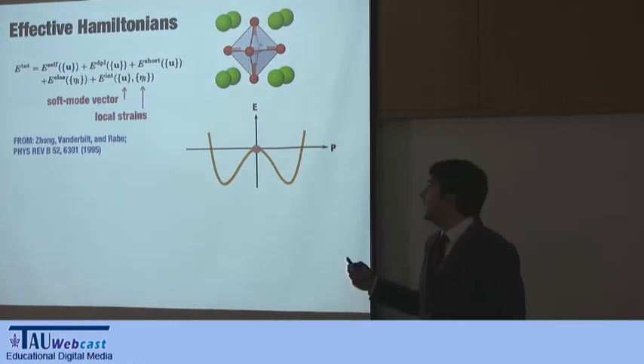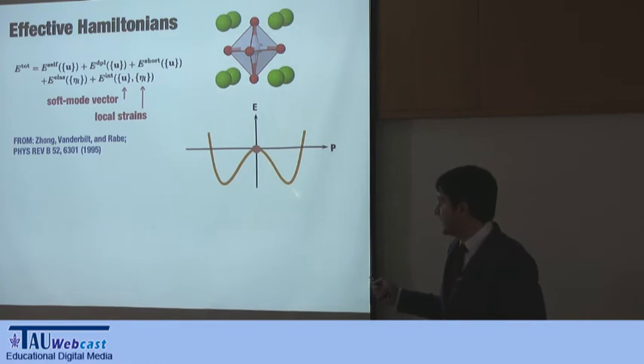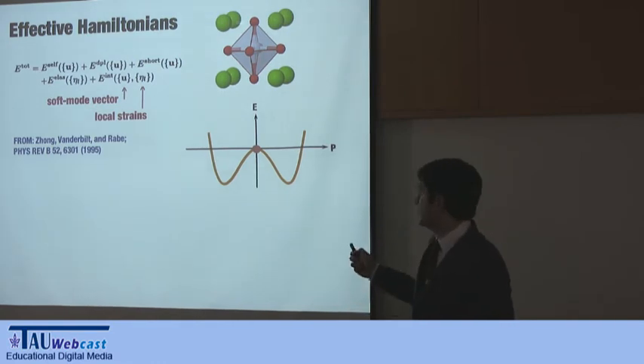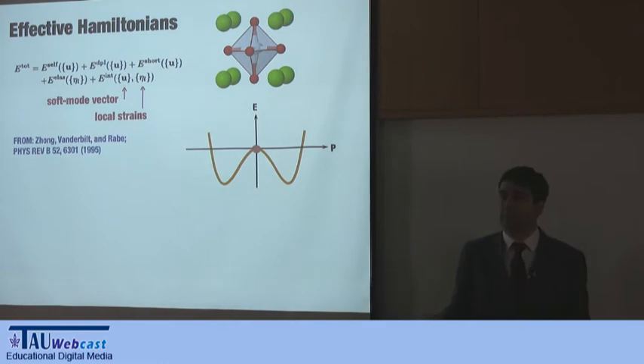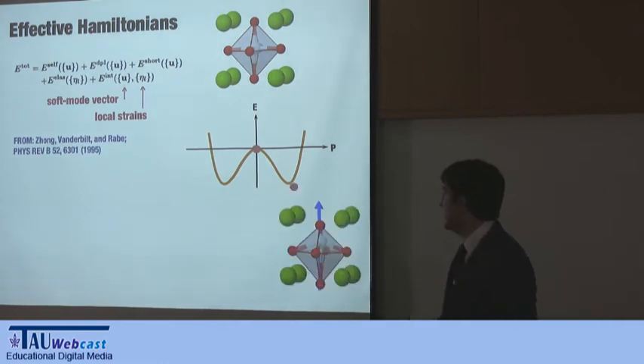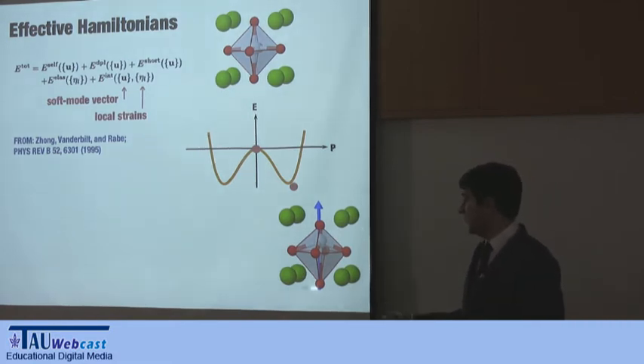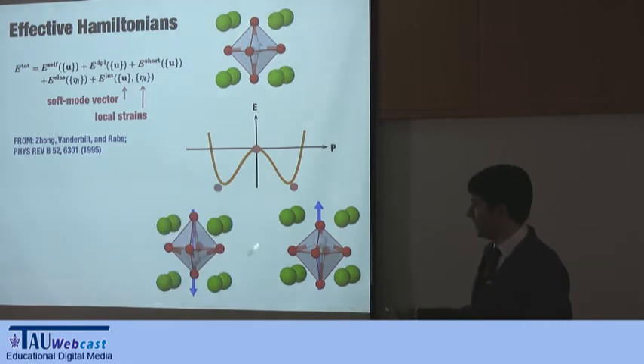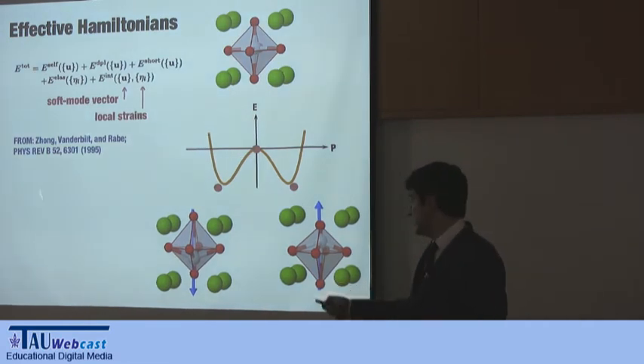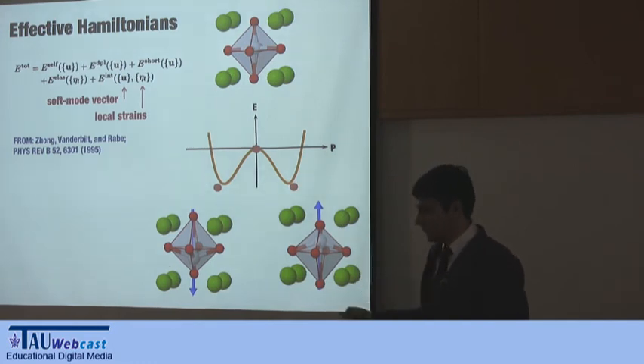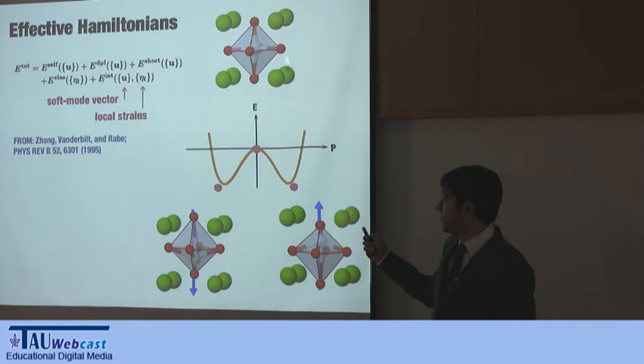Now, how good is this? It says that there is a minimum here. Okay? And this should correspond to the polar structure for the theory to be perfect. It doesn't correspond exactly, but it's very, very close. So if you look at what happens to the material in the polar structure, the displacements are very, very similar to the ones that the atoms want to do there. So you get a point here, and obviously you get the other configuration, so you get that other minimum. Because these reproduce the real minima so closely, you can use these displacements as your variable.